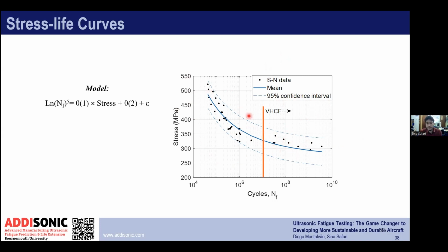As you can see, we can fit these data again using regression or a simple model, and find out the trend with some confidence interval. And just take into account that this very high cycle fatigue regime with normal machines will take, as Diogo mentioned, up to 1 billion cycles. It will take 1 year to do just one specimen. But with this machine, it's achievable with just 12 specimens. We can find out these data points and build this stress-cycle, number of cycles curve.